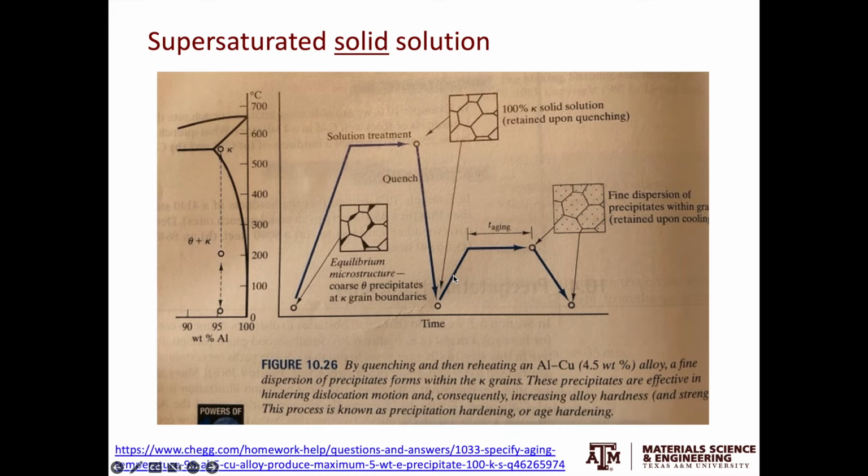Next, you heat up the material slightly at a lower temperature compared to the solution treatment temperature, and you will have precipitates dispersed throughout the microstructure. The heating or aging here is analogous to the small perturbation you introduce to the supersaturated salt solution. The idea is to bring out the excess amount of solute in the form of precipitates.